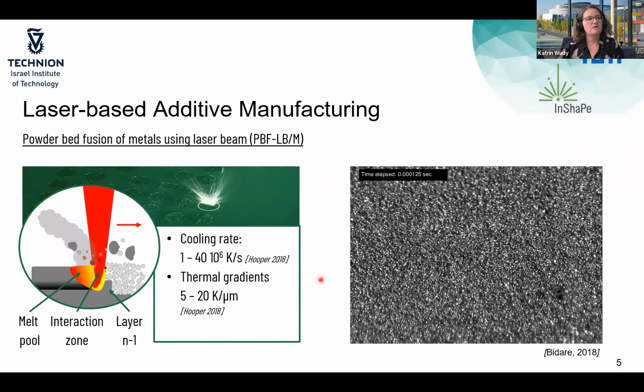For this purpose, we solve an optimization problem, which measures the difference between the measured signal in red and the simulated signal according to Planck's model in blue. We need to minimize this objective function, and once we minimize it, we achieve an estimation of the temperature and the emissivity of the material that we are investigating. Can you go ahead, Katrin, please?